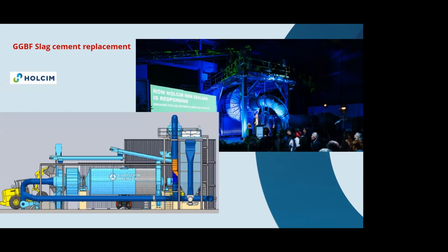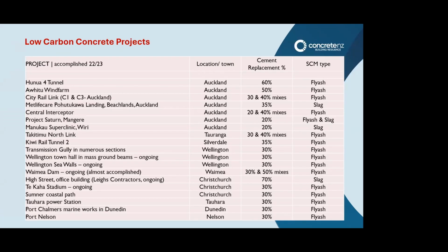So a couple of projects have been done with low carbon concrete. At the Hunua 4 tunnel, we have used fly ash. We actually achieved a 60% replacement. City Rail Link, one of the very prominent projects, 30 and 40% fly ash mixes have been used. The highest cement replacement so far was achieved by Leigh Contractors, in a project still under construction in Christchurch on High Street. It's an office building where they have replaced 70% of the cement.